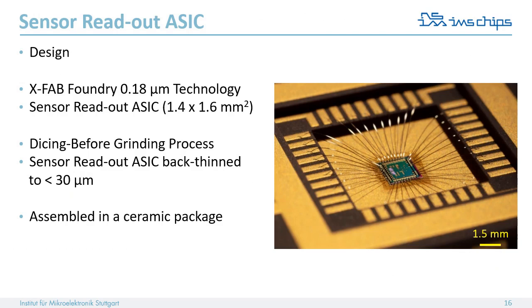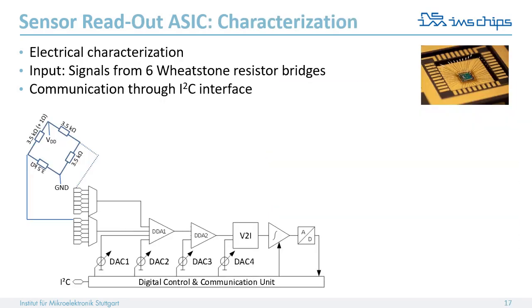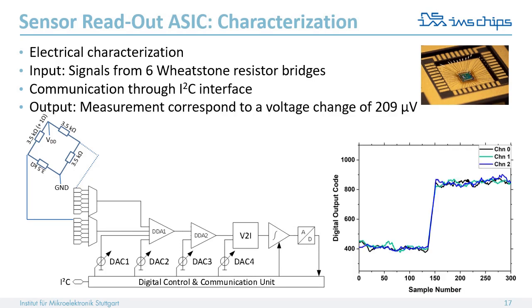Now I will continue to present the sensor readout ASIC. The ASIC was fabricated at X-FAB foundry using 0.18 micrometer technology. The ASIC was back-thinned in our institute down to less than 30 micrometer by using the dicing before grinding process. For the initial testing, the ASIC was assembled in a ceramic package, shown in the photograph on the right-hand side. The signals from 6 Wheatstone resistor bridges will be measured through I2C communication, depicted in a simplified schematic below.